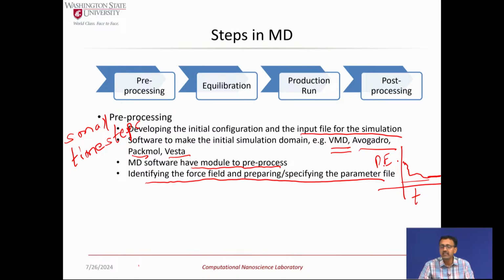The other is you can equilibrate in steps. You can first do a static energy minimization, which is essentially a 0 Kelvin energy minimization, but it's not DFT. You're still doing that based on the force field that you have specified, but you're doing it without capturing any dynamics. There's no time step. And then you follow that with, so you have a crystal structure. I'll show you an example later for an aluminum crystal. And you start off with a lattice parameter that is off.